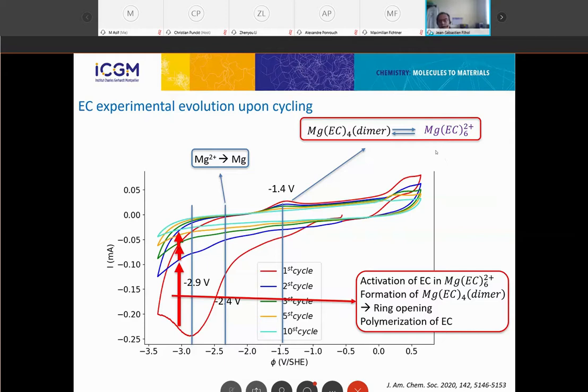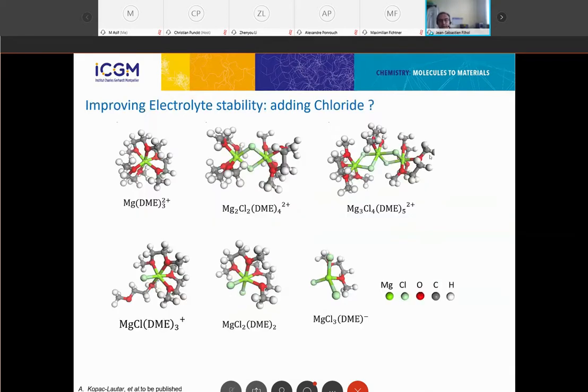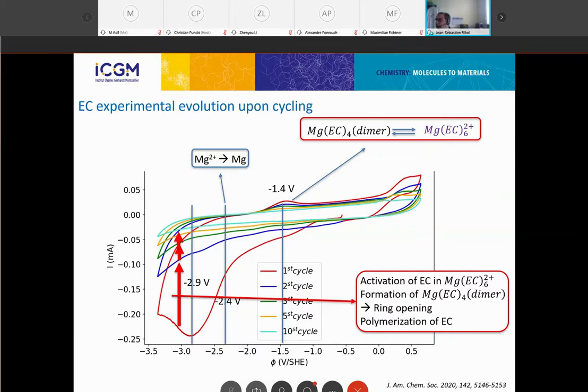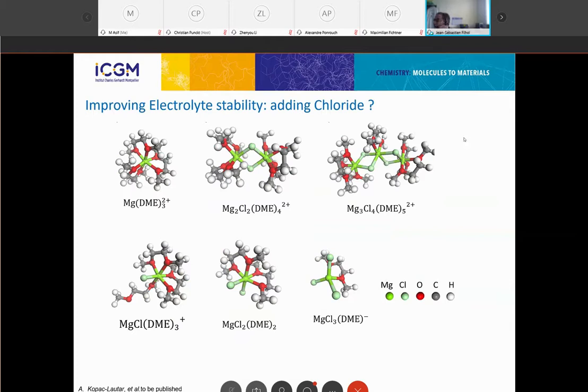So to summarize this part, mostly what is annoying is DME is not stable enough under reduction and will just break down. And ethylene carbonate could be stable, but the problem is it undergoes strong activation and you go to polymerization and you are passivating your whole electrode by creating something polymer. So good question is, how can we prevent that? One proposition was adding chloride to your electrolyte and to form different kinds of magnesium chloride that we compute.